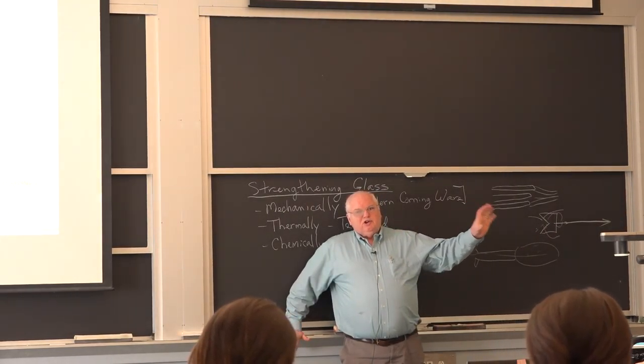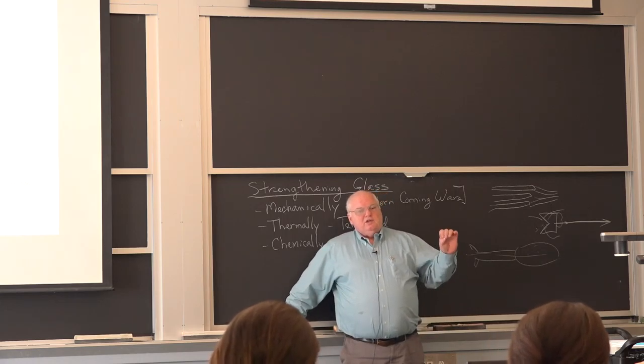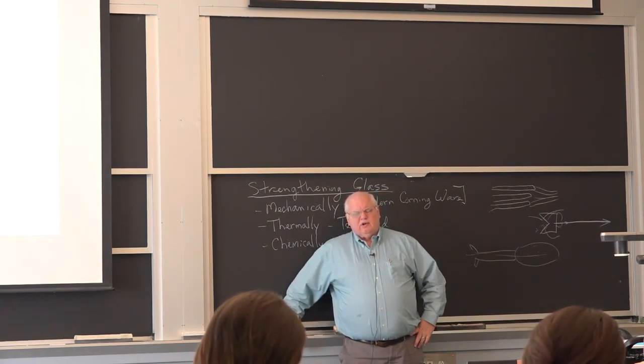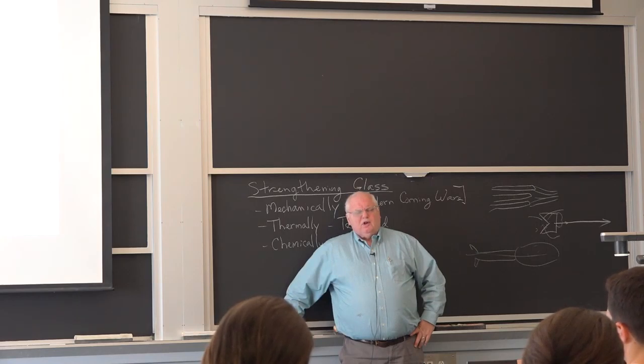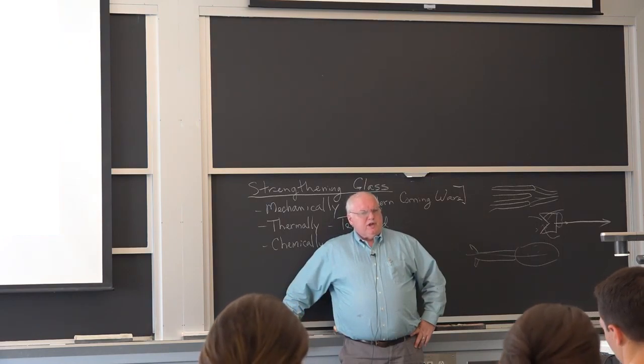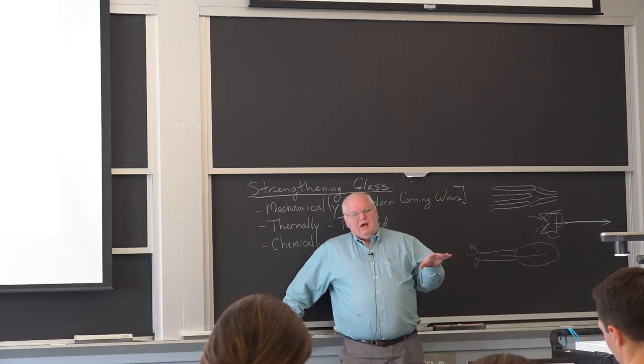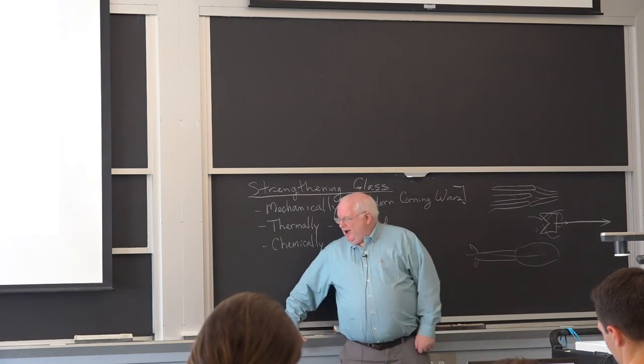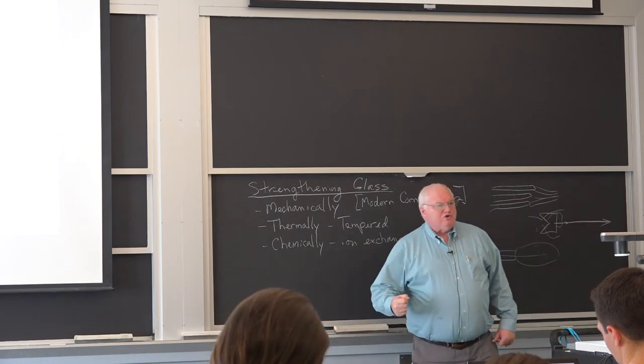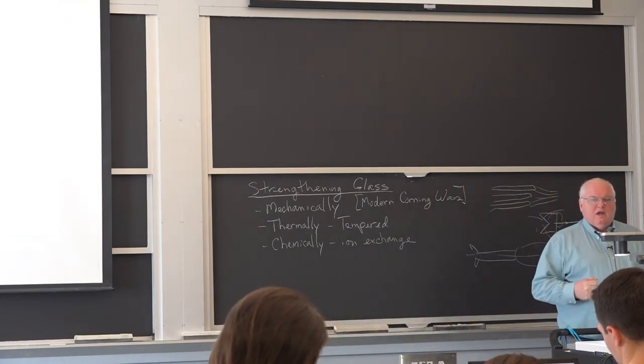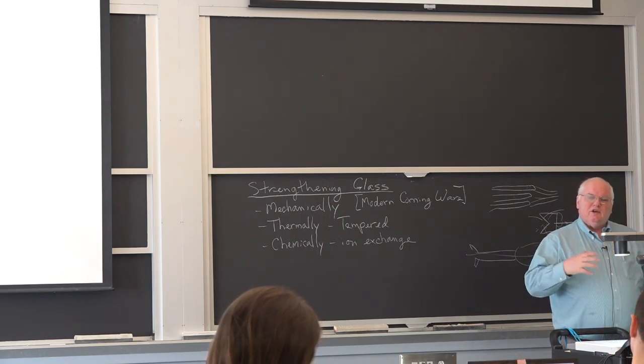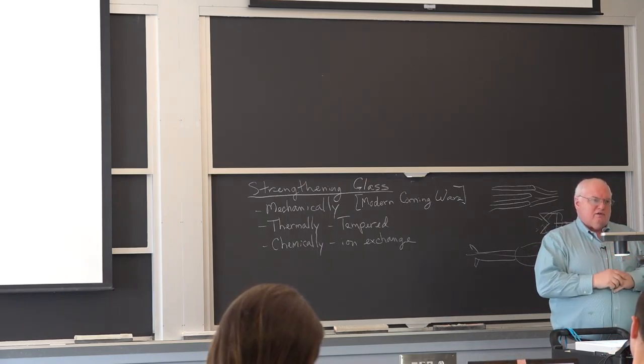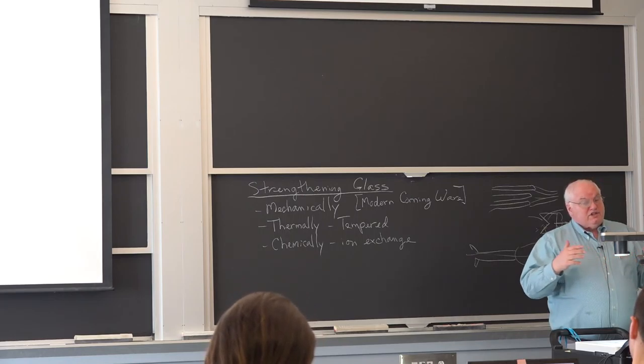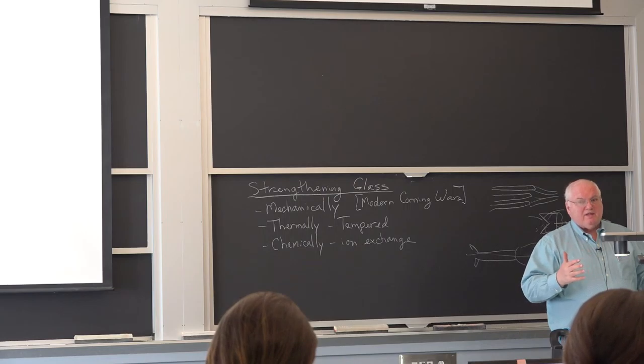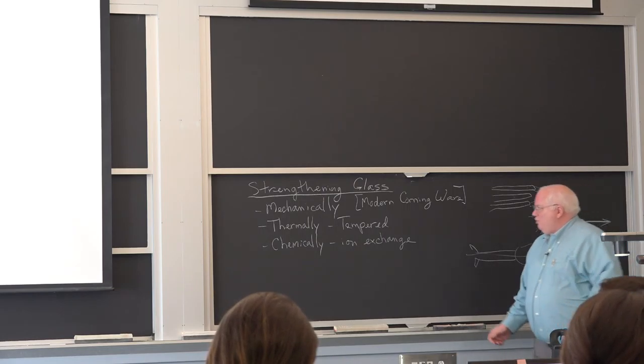You take the glass, you finish making it, and actually it's not just a regular piece of glass, it's a piece of glass with a lot of lithium oxide rather than sodium and potassium oxide. And you put it in a heated bath of some potassium and sodium salts. And by ion exchange, the lithium gets replaced by larger sodium and potassium atoms. And you can create a compressive residual stress by having a compositional gradient. You diffuse it in. This takes days in a hot bath to get chemical tempering of the glass.